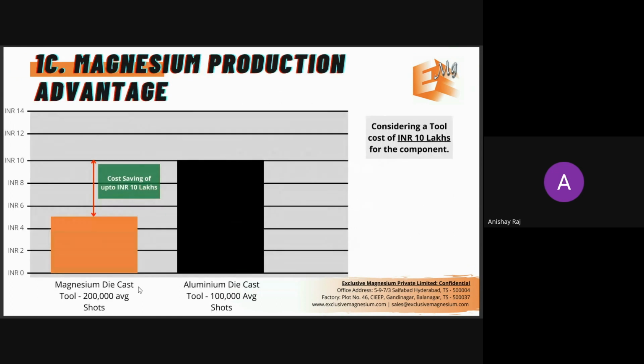The third factor when it comes to cost is the die cost. So when you look at something like die casting, an average aluminium die would give you somewhere around 1 lakh shots. Whereas because of the low affinity of magnesium to steel, you'll get about double of that at a minimum when you're working with magnesium. So if the die was costing you about 10 lakh, you're directly saving 10 lakh rupees just in the die, because you can run the die for much longer.